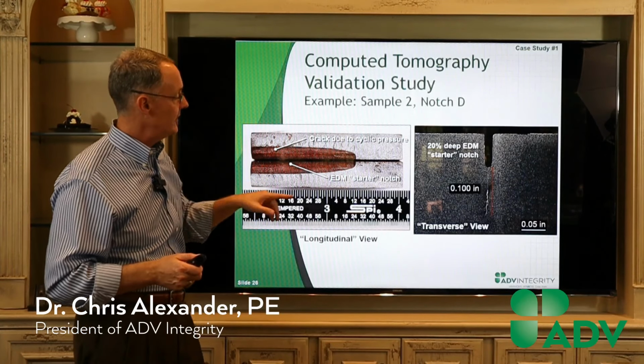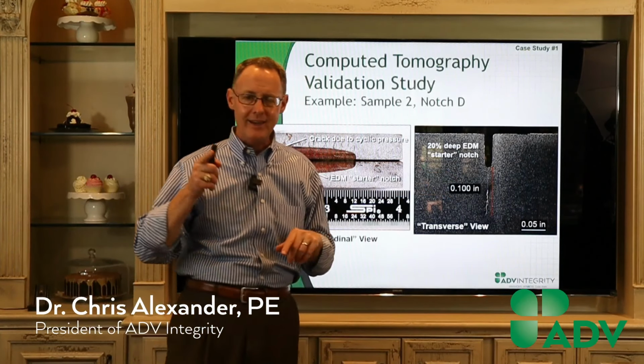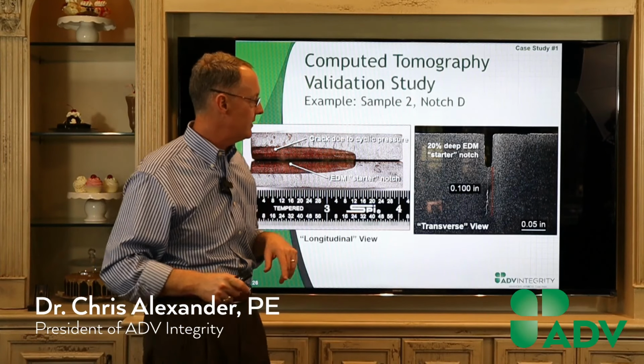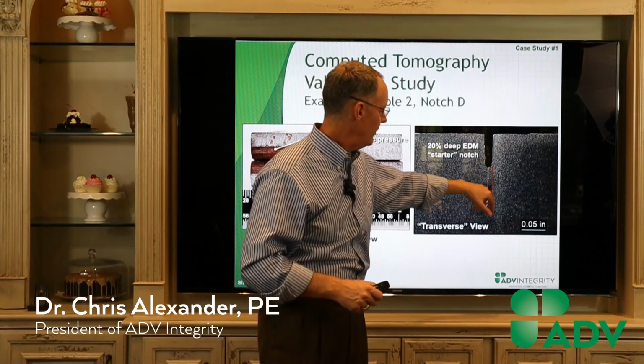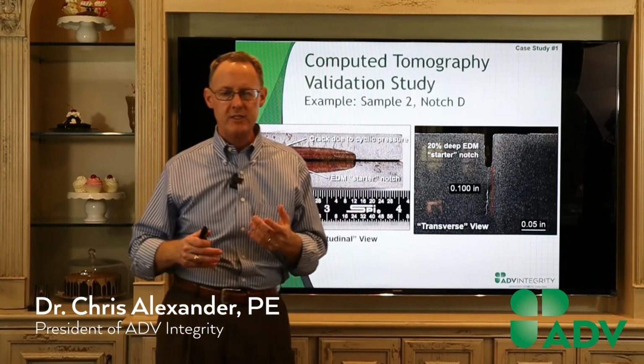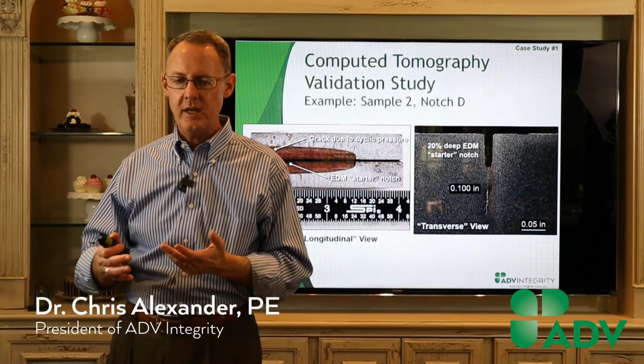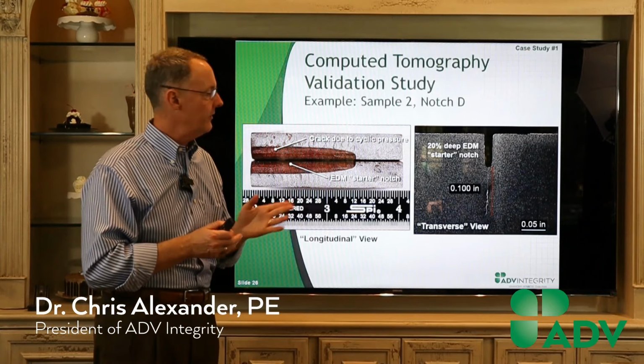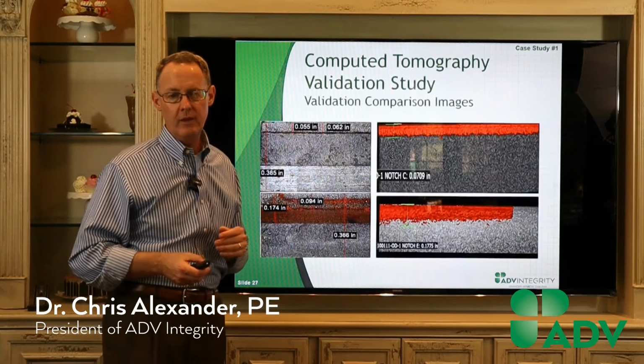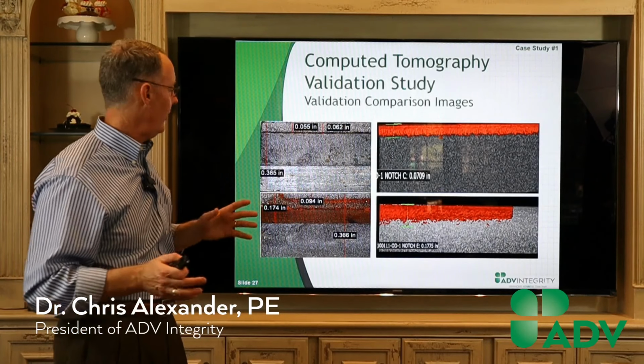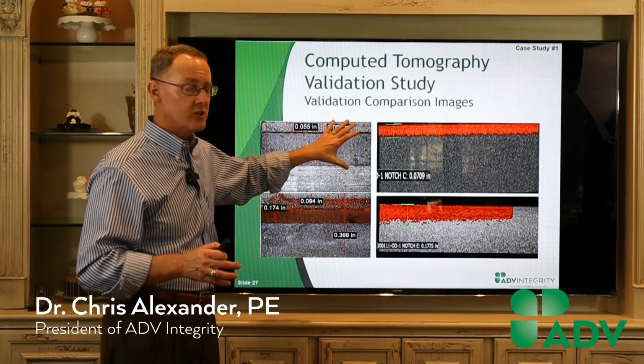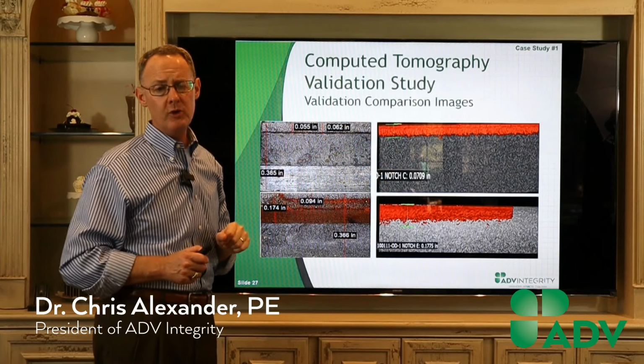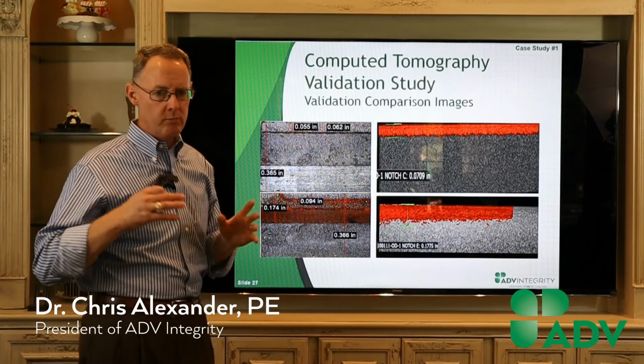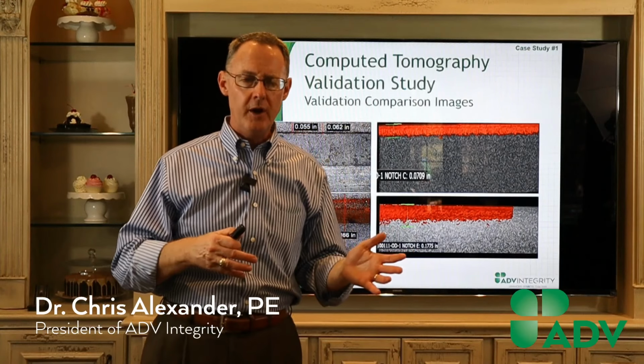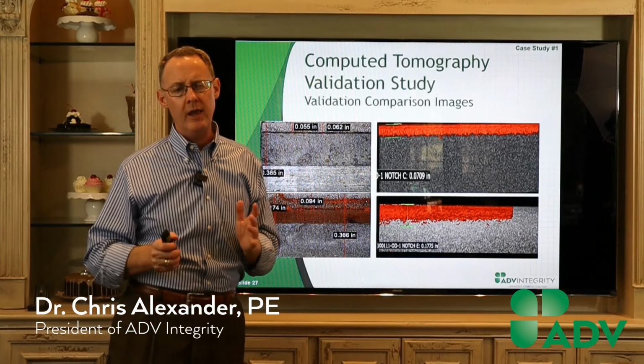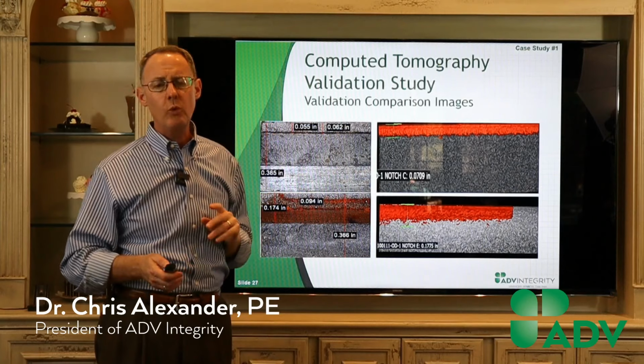We sectioned it, and so this image on the right is looking down the axis of the pipe, and what you notice is this EDM notch has turned into a crack. And so it's relatively easy in one sense to see a notch. A very tight crack like this is definitely more of a challenge. And so this next slide, we're comparing what we get under a microscope to the right, where we have the images from the computed tomography. And so we broke a bunch of features open, we did a comparison, and then basically we created a plot that showed what did we measure versus what do we really have.